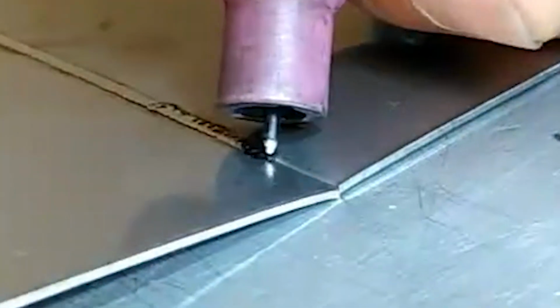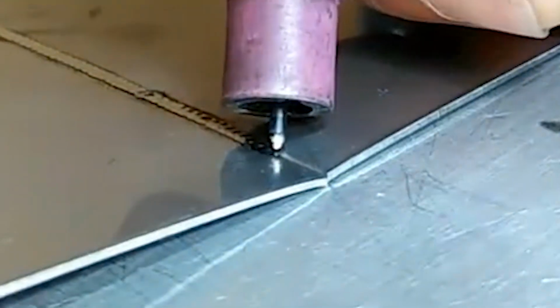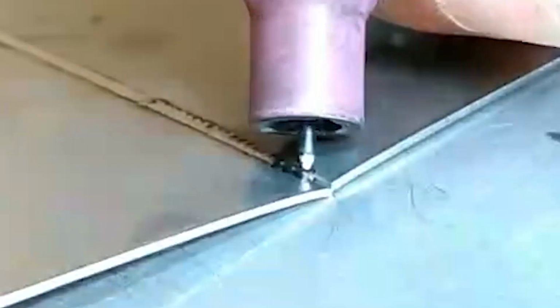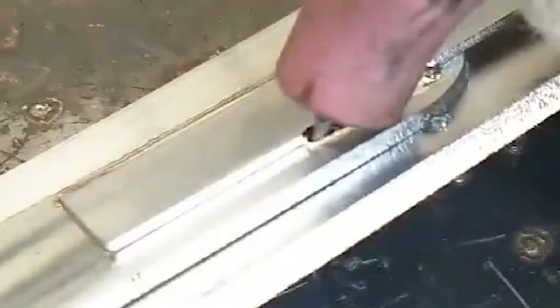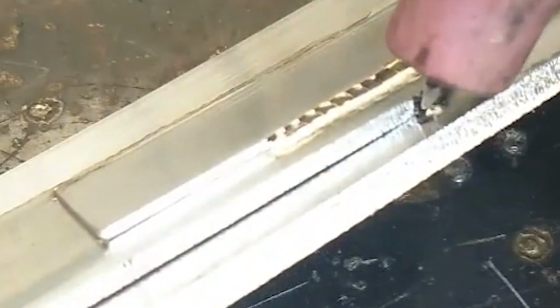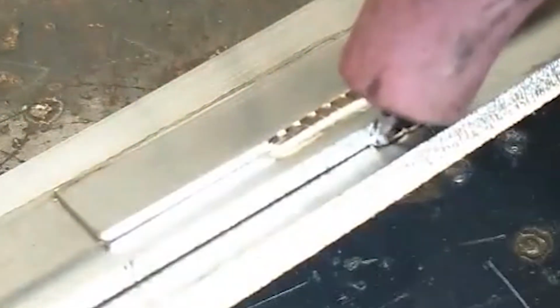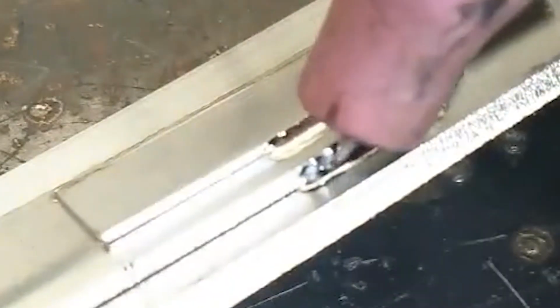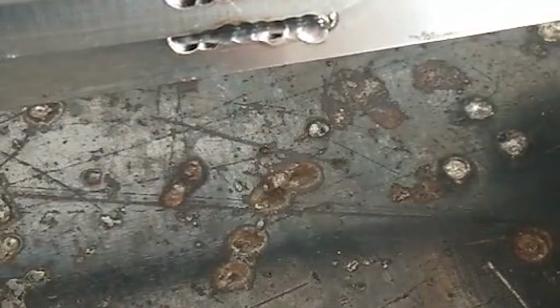Due to the special functions of the cold welding machine, the following functions can also be realized: 1. Repair welding in the mold industry: 1. Injection mold, 2. Stamping mold, 3. Die-casting mold, 4. Rubber mold, 5. Copper alloy mold. After repair welding, the mold can be subjected to various machining, heat treatment and nitriding treatments. Using different hardness materials, different hardness after welding can be obtained, for example, 60 HRC. Welding repairs can also be performed on the toughness of the cold die and the cutting edge of the tool, eliminating the complicated preheating and heat preservation process of ordinary argon welding.